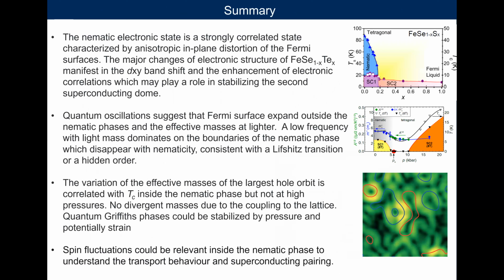So I presented the behavior of the nematic electronic phases of two families of iron-chalcogenide superconductors. I showed the information we extract from Fermi surfaces and how they change inside the nematic phases, how we detect this unusual dominance of a low frequency which disappears together with the nematic phase, and changes in the magnetotransport in the same regime, and the lack of divergent effective masses at the nematic endpoints due to the finite coupling with the lattice, and the potential stabilization of Griffiths phases in that regime. And I think many of the features we observe and the unusual Hall coefficient behavior point towards very likely strongly anisotropic spin fluctuations that need to be understood to explain the complex magnetotransport behavior. Well, thank you very much.